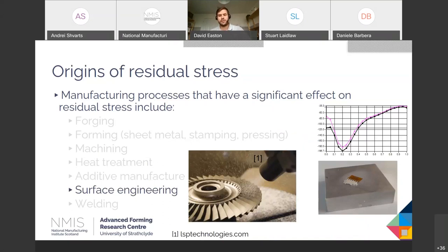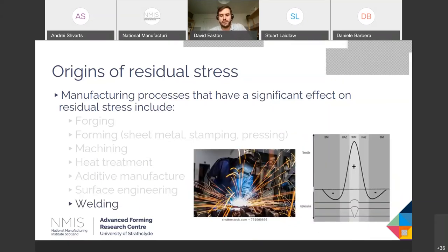Surface engineering, I mentioned previously, this is where we're intentionally introducing residual stress in order to get some sort of benefit, whether it's fatigue or corrosion. And welding. Welding is a technology we see across all sorts of manufacturing environments, all sorts of industries, and inevitably it's going to lead to residual stress. We have very high heat input, and we can have dissimilar materials, the part's going to heat up and contract, and that's going to leave behind residual stress. Depending on the situation, depending on the application, we may need to address that.